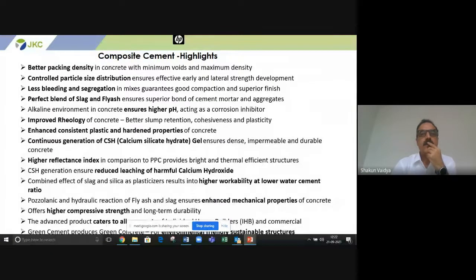So highlights of this blended variant of cement: better packing density, as I told you, and controlled particle size distribution. Cement is good when the maximum particles fall in between 3 to 30 microns. So it has a controlled particle size distribution as well. Less bleeding and segregation. So mixes are much more cohesive and workable.